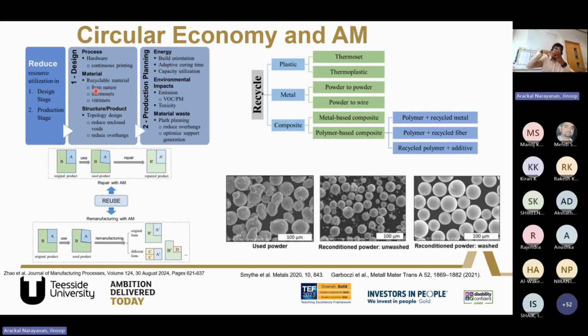Enclosed voids trap the powders a lot, so we can design the product in such a way that the powder can be easily recovered from the product. Then we can reduce overhang, so that we can try to optimize the overhang required for a design, so that we can reduce the reliance on overhang structures and then reduce the material usage.